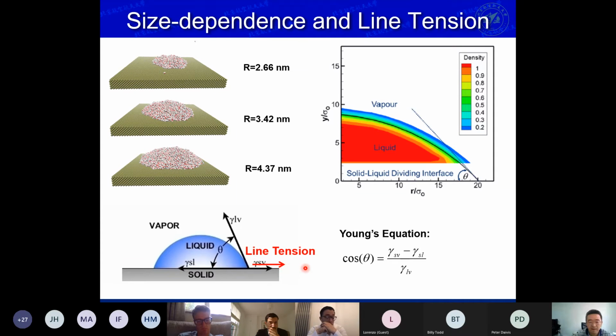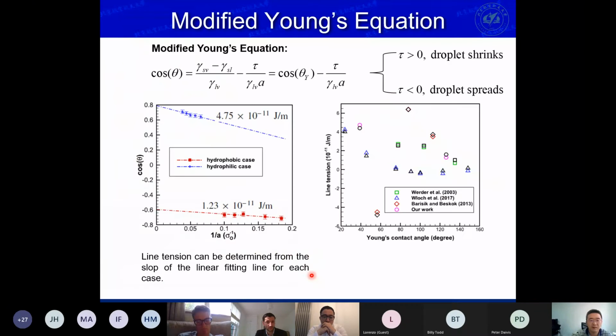The line tension is the excess free energy exerted on the contact line. Because of the line tension, Young's equation has to be modified like this. Here, tau is the line tension. We can see that if the line tension is positive, the droplet will shrink and the contact angle will become bigger. Conversely, if the line tension is negative, the droplet will spread and the contact angle becomes smaller.